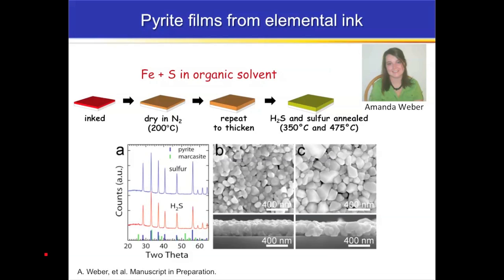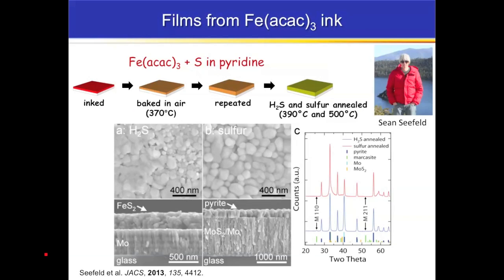And we ensure that we have phase pure pyrite to the limit of detection of all the techniques available to us. The second molecular ink approach uses iron 3 ACAC, just like the CVD chemistry did. We add sulfur to that, and we use pyridine as a solvent in this case. And this is the end result here.